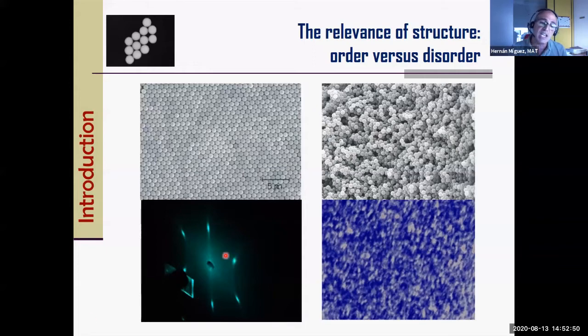So same composition, completely different structure, and therefore completely different optical properties. If we shine light on them and put a screen at the back of the sample or in front, if we make a hole, we can see clearly how the order is reflected in the optical properties. You see this diffraction very clearly, right? On the other hand, if you do the same with this disordered material, you get something completely different, which is this speckle pattern, right? Characteristic of an optically disordered material. So structure means everything in terms of how they interact with light.